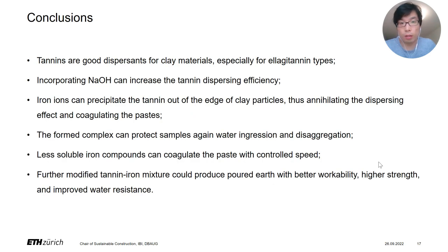So yes, this is my conclusion. In short, tannin can be used as a dispersant, and further incorporating sodium hydroxide can increase the dispersing efficiency, and iron ions can remove this dispersant effect, and the complex can provide some water protection of the sample. And then we can control this complexation reaction by using less soluble iron component, and with this kind of platform, we can employ other modifications to produce poured earth with better workability, higher strength, and improved water resistance.